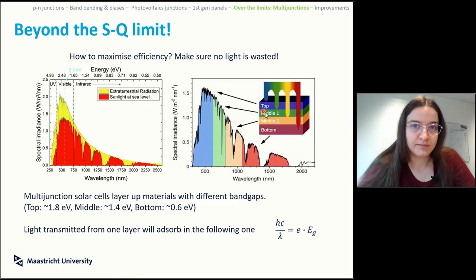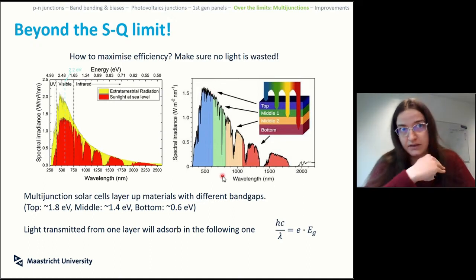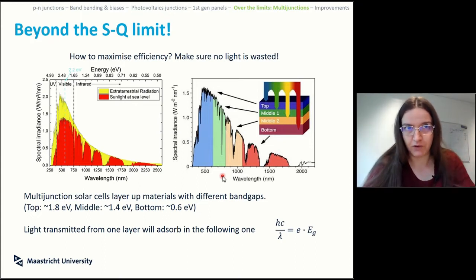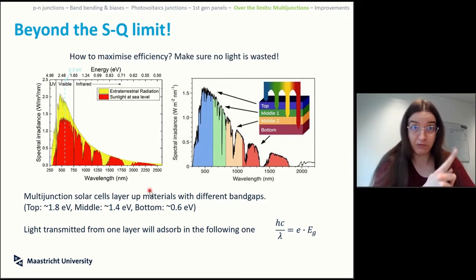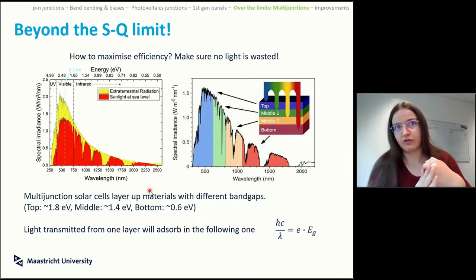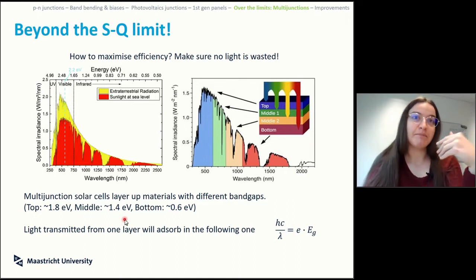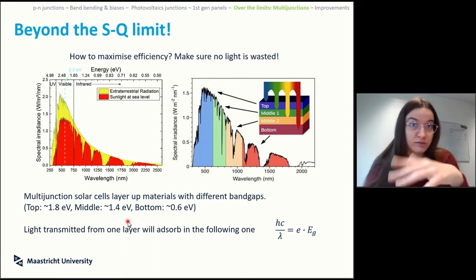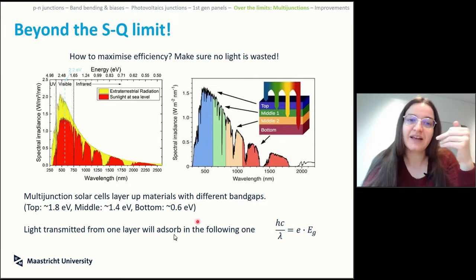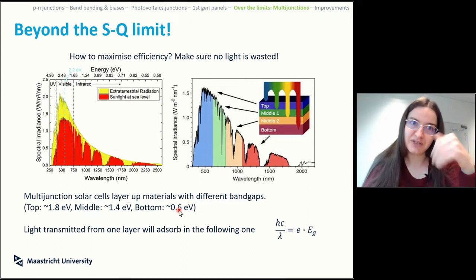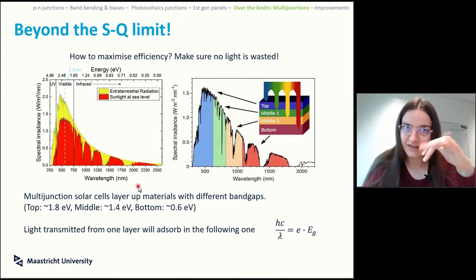And imagine if you were to have a top material that absorbs at 1.8, then anything that is from 1.8 higher gets cut off because it gets absorbed by that material. Call it a day. Anything that is lower than 1.8, so imagine you are here at 1.8, everything that goes lower, so all the rest of the light passes through. You catch another material that is at 1.4, anything that is between 1.4 and 1.8, because 1.8 was absorbed before, will get absorbed by the second material. And everything that is below 1.4 will again pass through the junction because it won't see any reason to get absorbed. And then if you have a bottom material with 0.6, it means that anything between 0.6 and 1.4 actually gets absorbed. Now, technically speaking, you could layer this as much as you want to make sure that you have the interconnection.